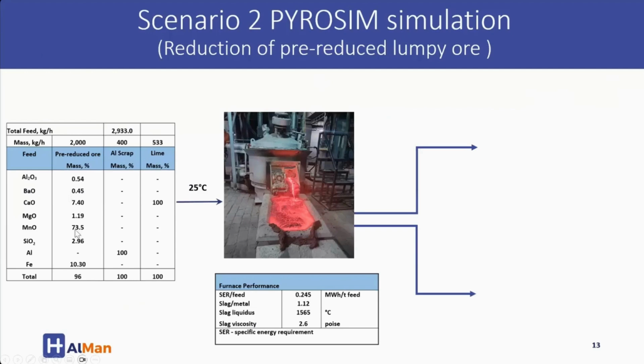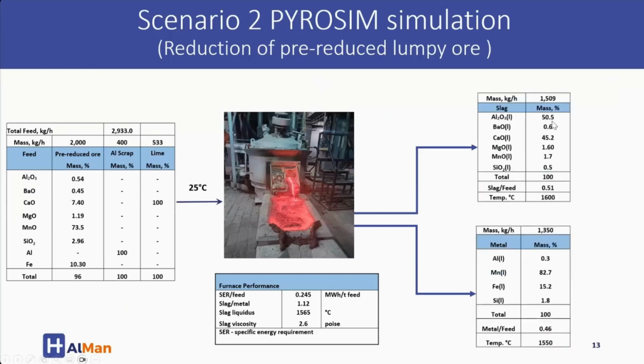You'll notice the manganese oxide in this material is much higher than the slag, and the silicon content is much lower. For this particular system, we're aiming to achieve close to 50% alumina in the slag.